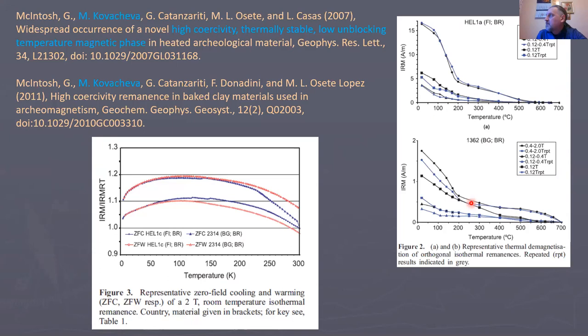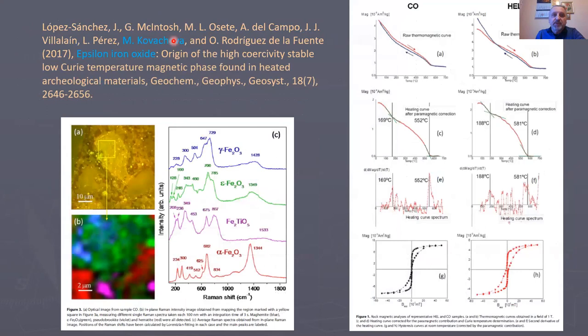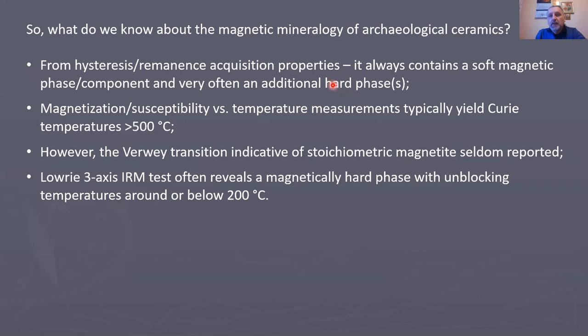Even more recently, Spanish groups, joined with Maria Kovacheva again, have suggested that this HCSLT phase could be related to a particular polymorphic form of iron(III) oxide, which is called epsilon iron(III) oxide. Okay, to summarize this introduction, what do we know about the magnetic mineralogy of archaeological artifacts?